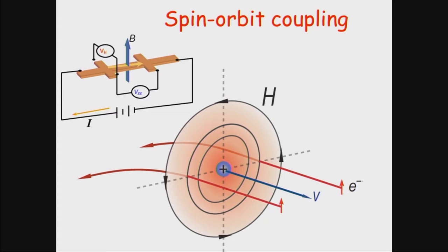When the electron passes through the solid, you see many positive ions. But if you sit on top of the electron, you see many positive ions moving toward you. And once the positive ions move, that's just an electric current. So along the current, there will be a magnetic field produced, and remember, it must be an inhomogeneous magnetic field. Remember that the electron not only has charge, but also a spin magnetic moment. So, exactly similar to the Stern-Gerlach experiment, the electron moving in this inhomogeneous field will be turned transversely. The electron on the right side turns this way because the magnetic field is pointing up, and the electron from the left also turns this way because the magnetic field is pointing down. So this is basically the hand-waving picture, and the rest is just quantitative analysis.